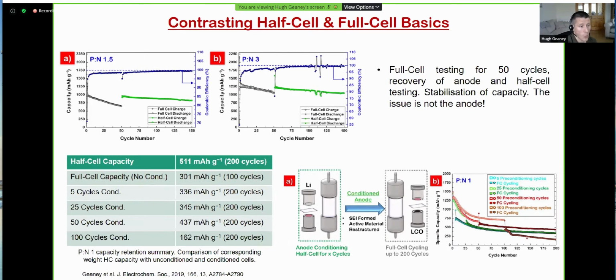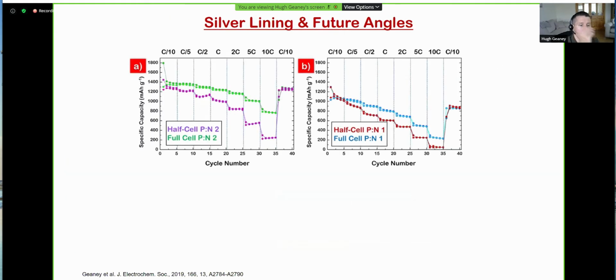Now, it is worth noting that this is still well below the theoretical capacity, or what we would expect for germanium. So obviously this is something that needs to be drastically improved in terms of the long-term cycling. One silver lining that has come out of the work in terms of the full cell performance is the rate performance, so how this battery behaves at high rate. Say 2C here means that the battery will charge in half an hour and discharge in half an hour. 5C again would be a fifth of an hour, and 10C then would be 6 minutes.